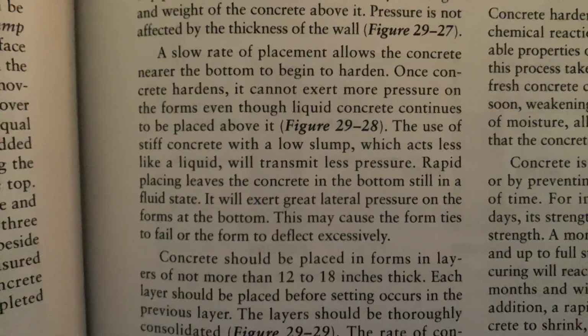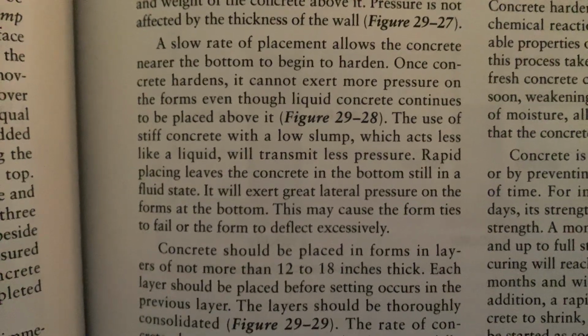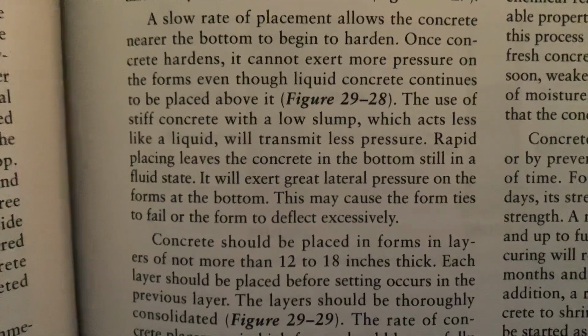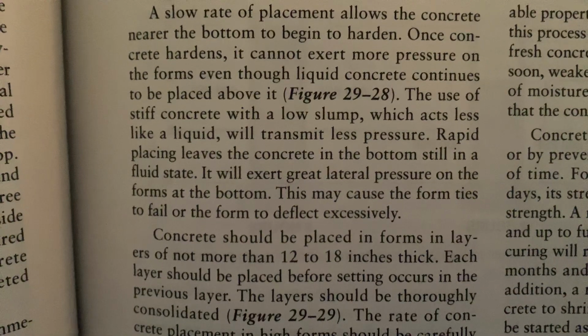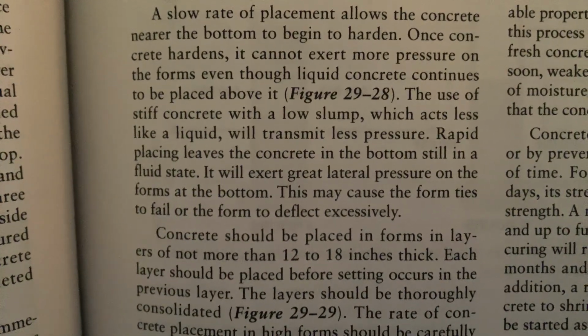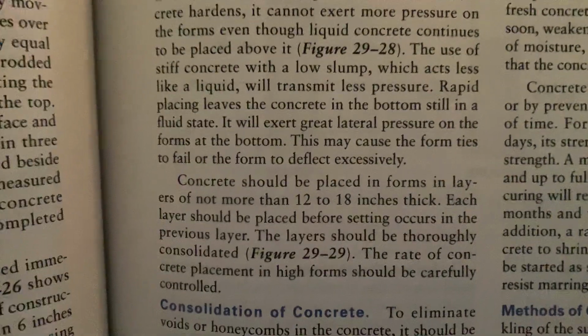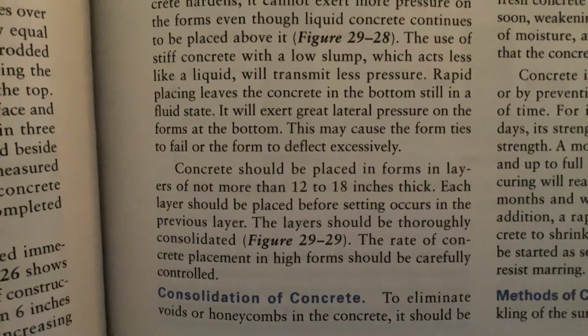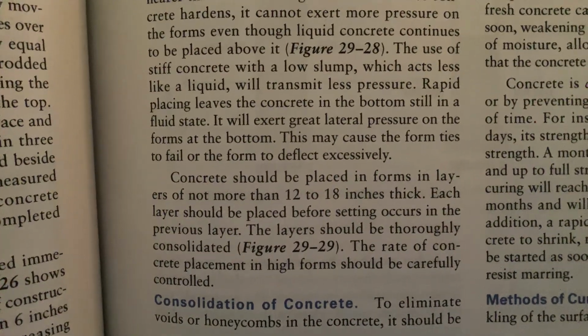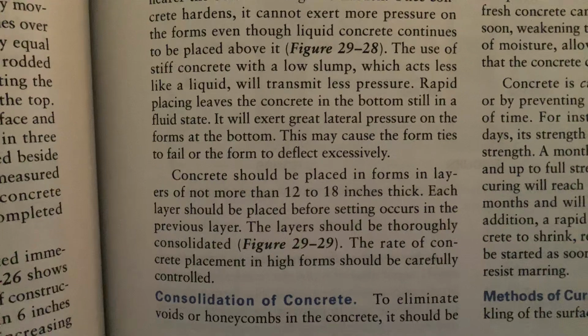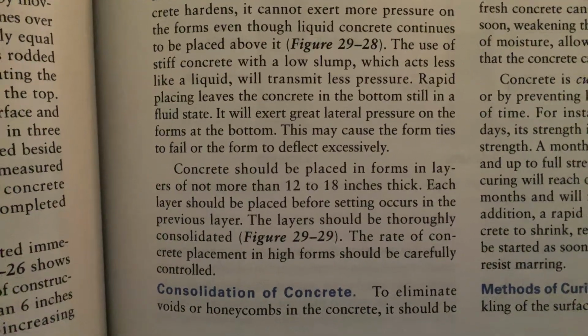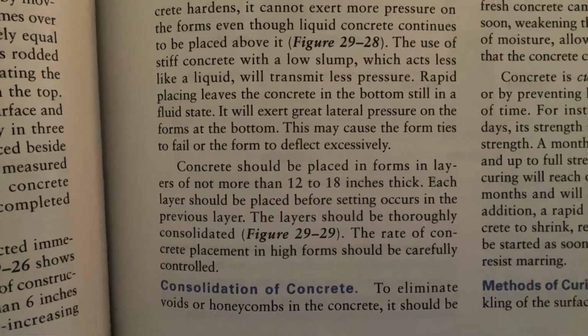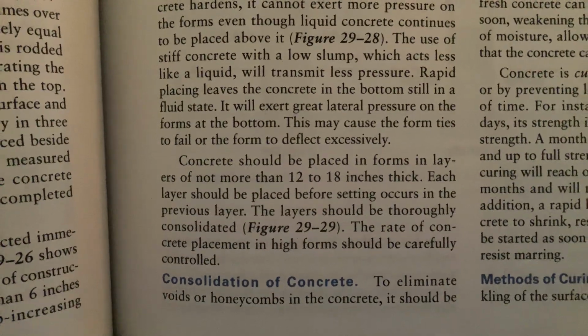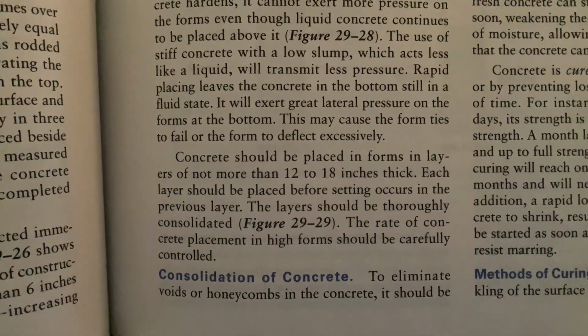Rapid placing leaves the concrete at the bottom still in a fluid state. It will exert great lateral pressure on the forms at the bottom. This may cause the form ties to fail or the form to deflect excessively. Concrete should be placed in forms in layers of no more than 12 to 18 inches thick. Each layer should be placed before setting occurs in the previous layer. The layers should be thoroughly consolidated. The rate of concrete placement in high forms should be carefully controlled.